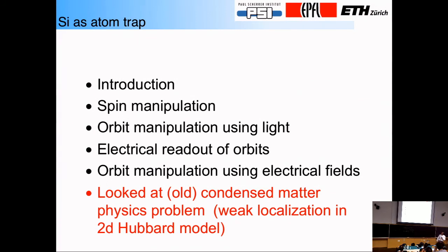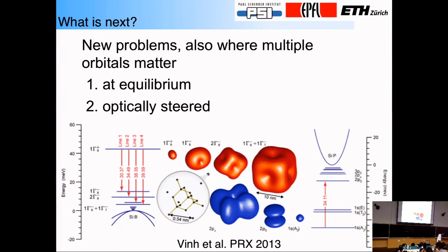Now, so that's silicon as an atom trap. Of course, what's coming next is, as I said, we're going to do deterministic things. And also, one thing to realize is that these systems in some ways map onto the Hubbard model, but there's actually a multi-orbital aspect to this, because the higher-lying orbitals are so much bigger than the low-lying orbitals because of this n squared, which is the scaling of the size of the orbitals with the principal quantum number. And this just shows you how these orbitals grow in size.